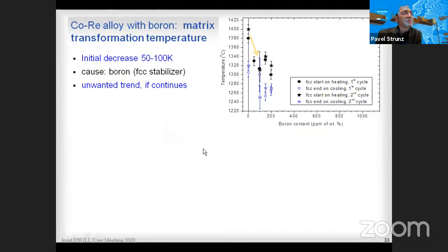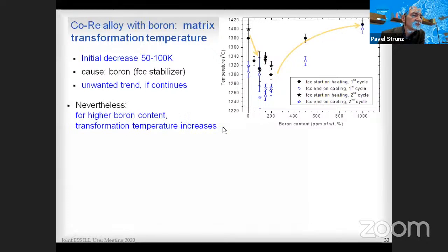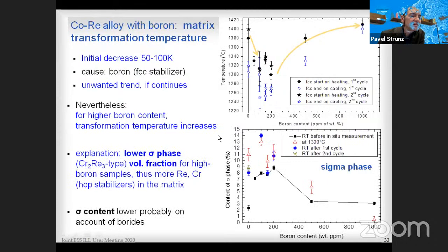Okay, when we plot the dependence of transformation temperature on the boron content, represented here by the black points and black stars, we see that initially there is some decrease, 50 to 100 kelvins, after adding boron. If it continued, this would be problematic, because the transformation temperature would be too low and the alloy would not be usable. Fortunately, this is not the case. For still increasing boron content, there is an increase of the transformation temperature again. And the reason for this is the sigma content, which is lower at higher boron content.